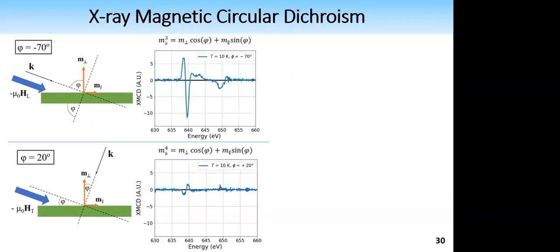Next, I want to discuss the grazing incidence measurements to construct two-dimensional vector diagrams of sublattice moments. Scans were taken at 2 incidence angles. This, of course, requires rotation of the sample, not the beam, in the synchrotron. However, for simplicity, I'm showing the diagrams in the frame of the sample. As an example, I'm showing the field being applied in plane. We were also applying the field out of plane. The 2 angles of incidence are 90 degrees apart: one was -70 and the other one was 20.